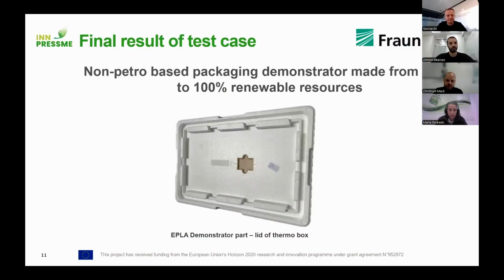And so what do we have in the end? The final result of the test case is a non-petro-based packaging demonstrator made from close to 100% renewable resources. In this case, it's a lid of a thermal box made mostly from PLA, with some fibers. And you also see here the data logger holder, which was 3D printed and incorporated during the production process.